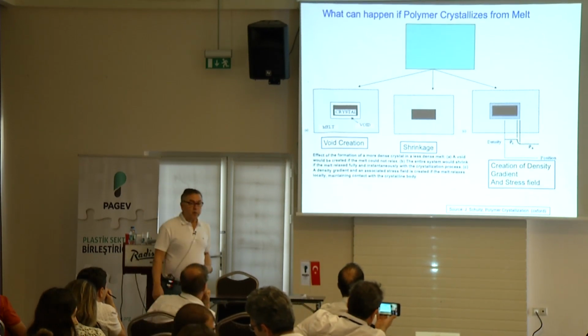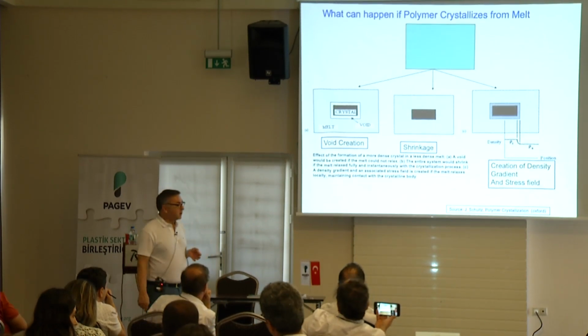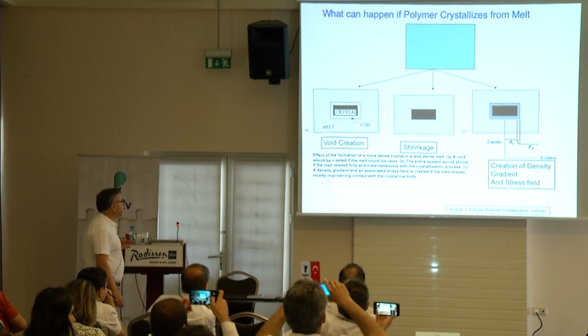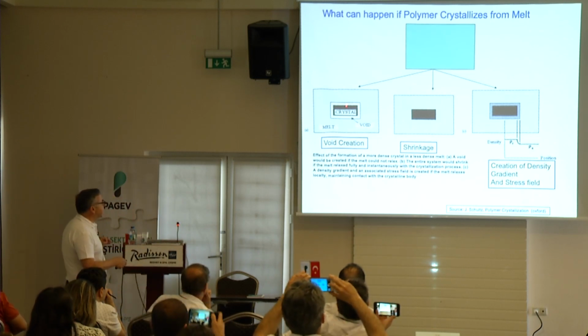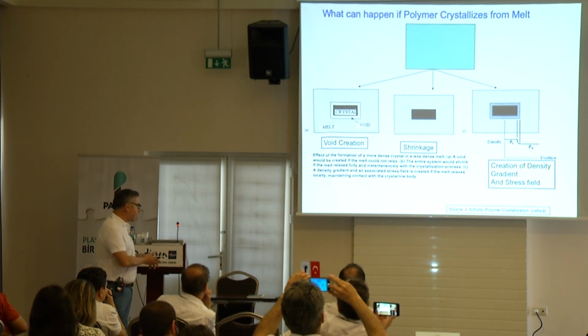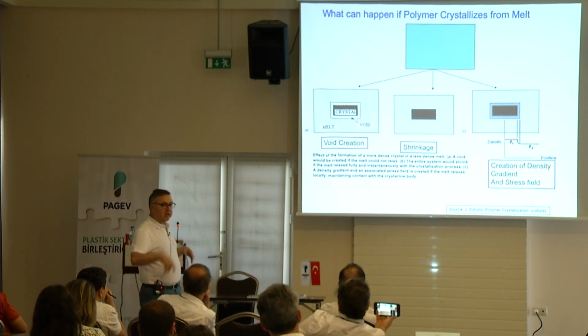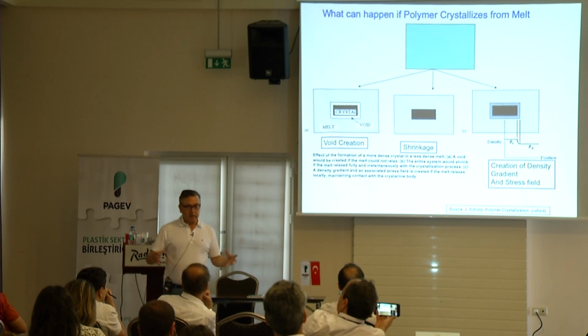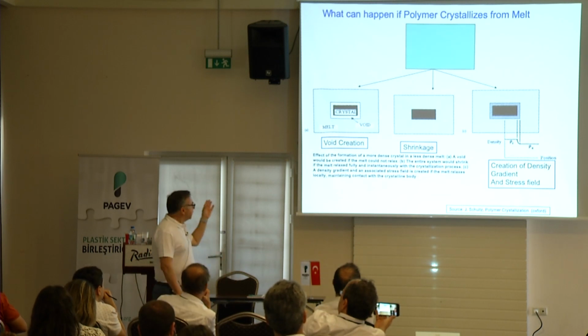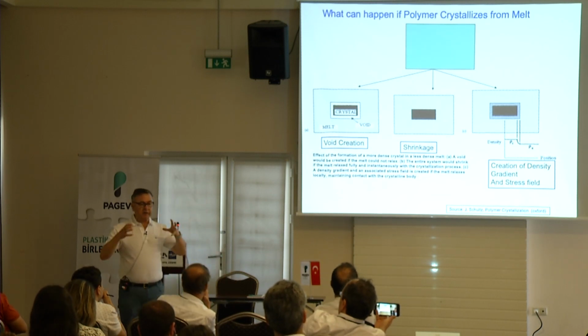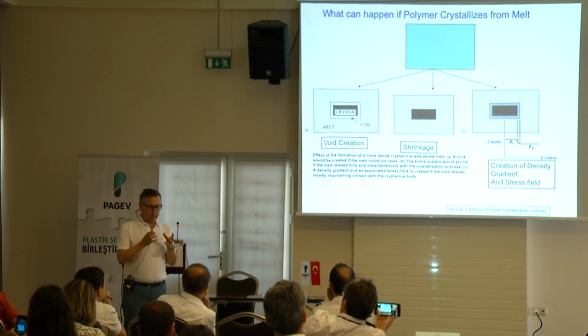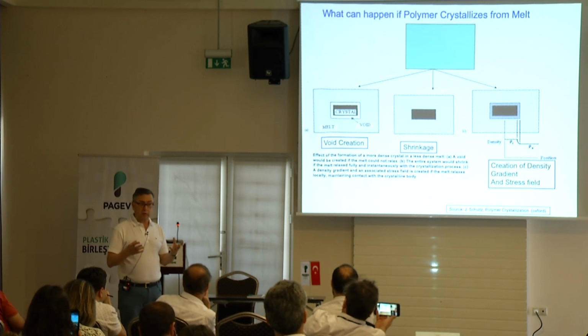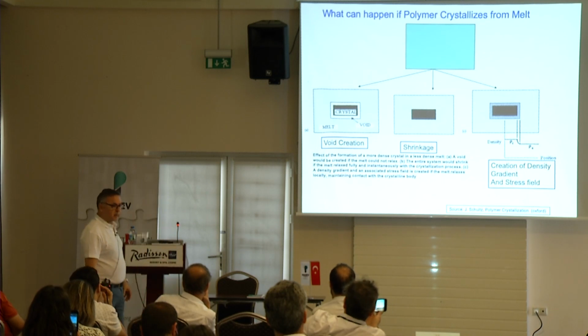So as Jakub was saying, shrinkage is an important part. When you take the material and put it into the mold, if you do a bad job of it, if you do too deep a quench into a very cold mold, you may end up with a void. Literally, the material breaks itself apart, and you've seen it. You say bubbles, what bubbles? And you think it's because of moisture that came out. No, literally the material rips itself apart as a result of that.